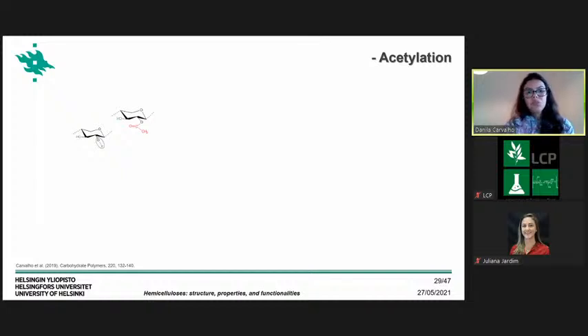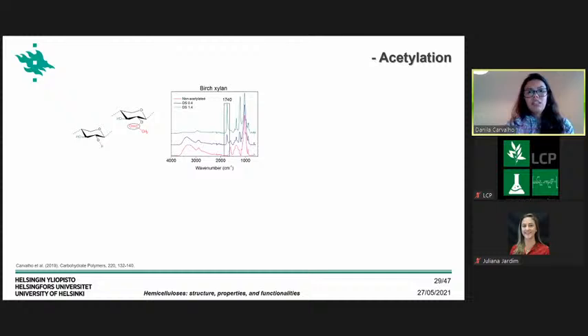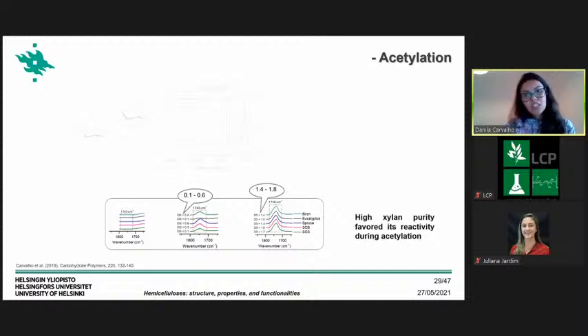During the acetylation, what we want is to substitute the hydroxyl group with one acetyl group. And we monitor this acetylation using FTIR. You could get different degrees of acetylation from low to high, proving that we can control the acetylation. And also one result that we got from here was that when the xylan was more purified, the reactivity during the acetylation was high.